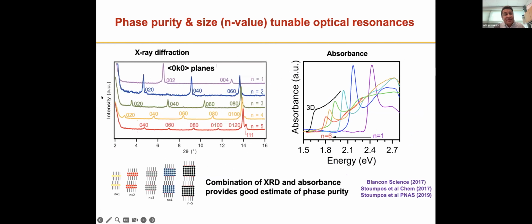So if you take an X-ray diffraction pattern of these crystals that you made, you'll get a pattern like this. And if you look at these low angle planes, which are these 0k0, which are along the z direction here, you can really characterize whether you made a crystal that is pure or impure.